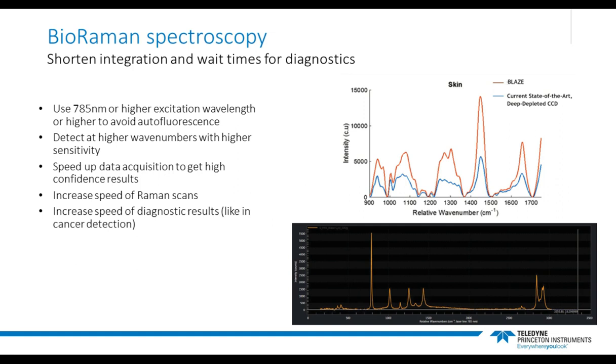So using HR sensors, the signal at even higher wave numbers can be detected with higher sensitivity. On the bottom right is an exemplary measurement of cyclohexane going out to 3,500 wave numbers. And on the top right, you see a graph comparing Raman spectra taken on actual tissue samples with an HR device shown in red compared to the current state of the art device shown in blue. One can clearly see the sensitivity advantage of the HR device, and that brings really tangible advantages, like a reduction of data acquisition times, so one can get high confidence results faster. That can be important to obtain faster diagnostics in medical applications, for example, like cancer detection or things like that.